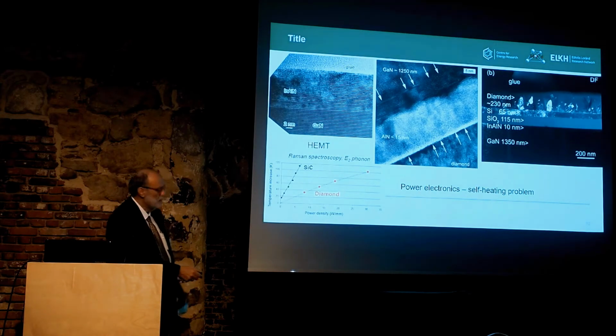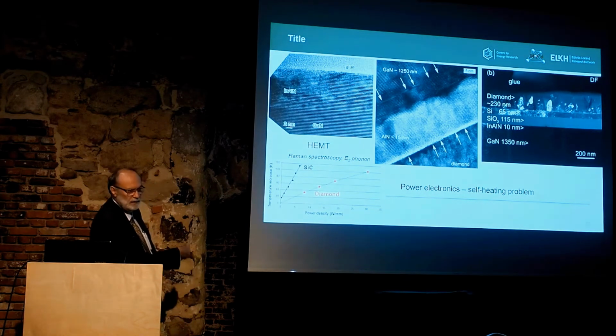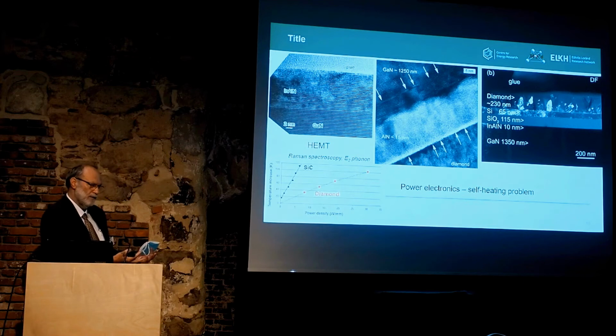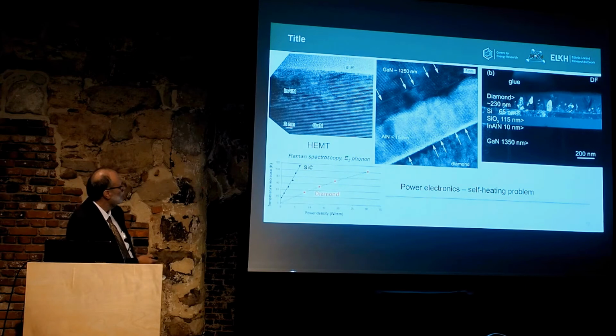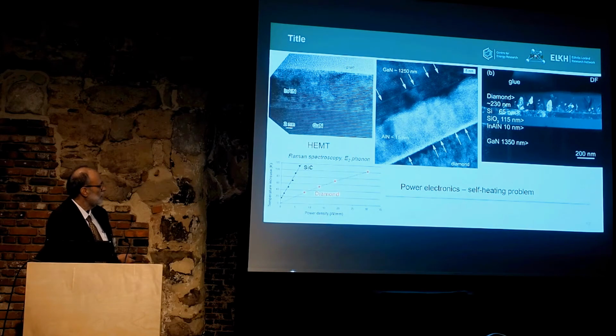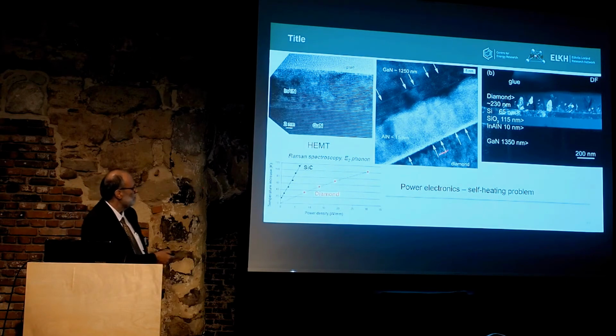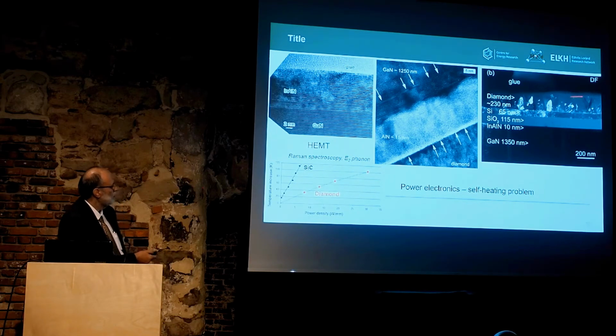Then we came to power electronics. In this gallium nitride power electronics, instead of the former milliwatts, now people are measuring the power in watts, and the power density is very, very high, which means there is a problem we face: self-heating. In order to decrease the self-heating of the device, which is not advantageous, we need a material which has very high thermal conductivity. The best one, or probably the best one, is diamond. So we studied nitride transistors which were grown onto single crystalline diamond. And we also had a transistor structure with a diamond layer deposited on the top.